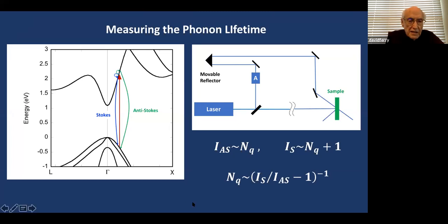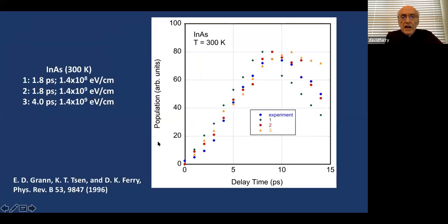Okay, now let's see, where am I next here? So this is now indium arsenide, but we're using that 1.96 eV laser, 0.6 of a picosecond pulse width, and we're measuring out here at 8 or 10 picoseconds afterwards. And why is it so slow that way? That's because the electrons with that high a laser energy go to the satellite valleys where they stay for several picoseconds, then they come back and start driving the phonons out of equilibrium.